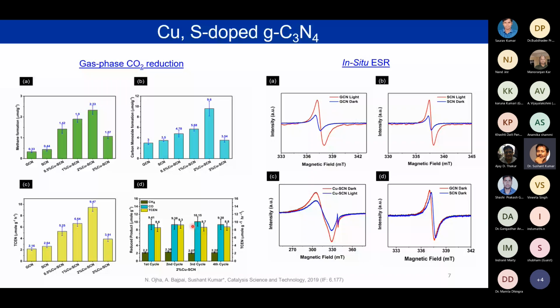Now we looked into the mechanism by which this reaction was happening. So we performed the in situ ESR with the help of IIT Bombay, and what we have seen is that the graphitic carbon nitride under the light has a more intense peak than under dark, and that is because of the free electrons in the graphitic carbon nitride, which are able to react. And the same is the case with the SCN.